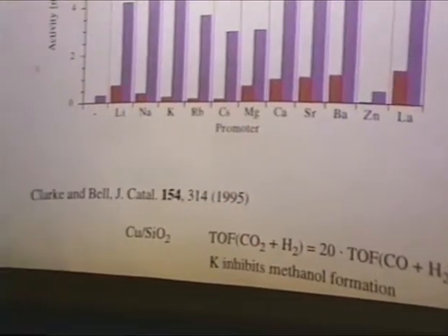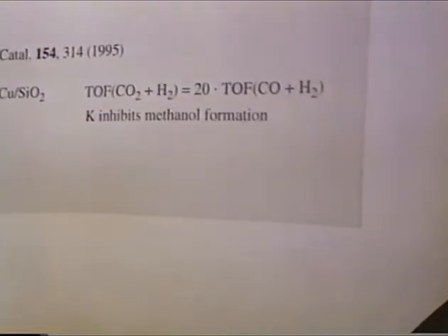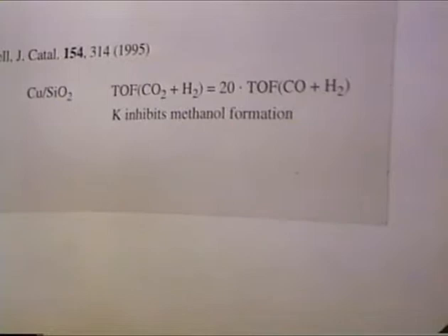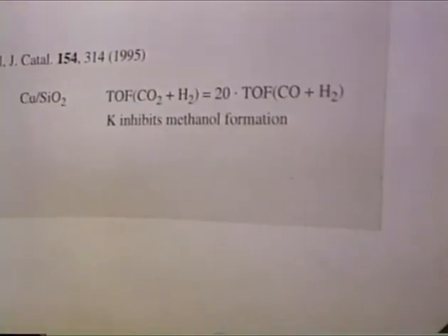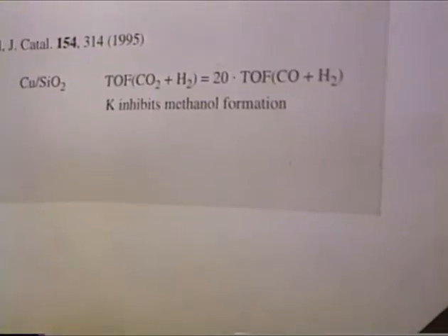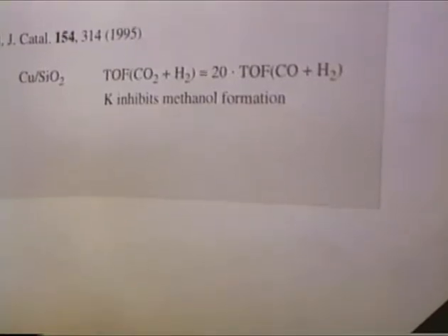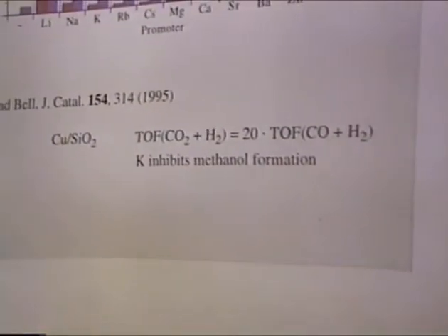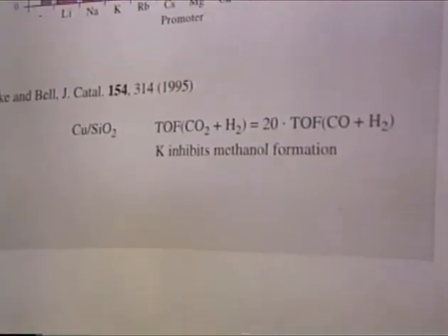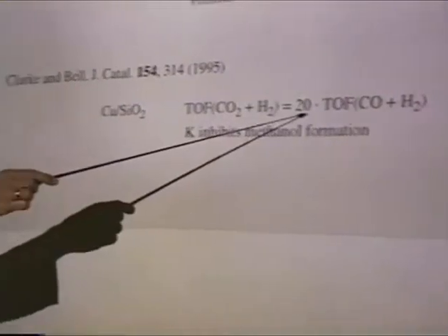Now in our case, that's absolutely not the case. It's well known that if you take a pure copper, for instance, Alex Bell and his student Clarke did this, you take a copper on silica with CO alone and hydrogen, you have a very low turnover frequency to the methanol. When you take the CO2, it's very much higher.